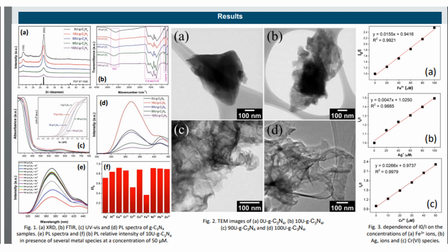According to the X-ray diffraction, all samples exhibit two diffraction peaks located at 13.1 degrees and 27.3 degrees in 2 theta, which are attributed to the repeated tris-triazine units and to the stacking of the conjugated aromatic system, respectively. These diffraction peaks can be indexed to the 100 and 002 diffraction planes of graphitic carbon nitride, according to the powder diffraction file 87-1526. Moreover, the intensity of the diffraction peak at 27.3 degrees decreases as the amount of urea precursor increases, indicating an increase in the degree of exfoliation of the layered material.